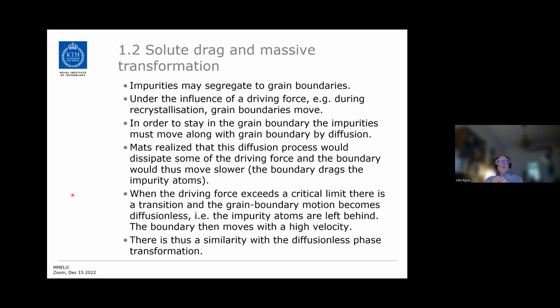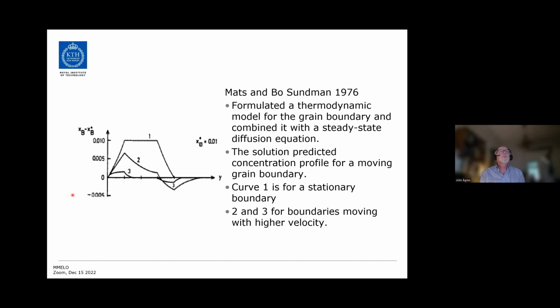And moreover, when the driving force exceeds the critical limit, there is a transition and the grain boundary motion becomes diffusionless, which means that the impurities, they are simply left behind. And then the grain boundary can move with a high velocity. So in a sense, there is a similarity with the diffusionless phase transformation. And that was, of course, realized by Mats. So Mats and Bo Sundman in 1976, they formulated a thermodynamic model for a grain boundary and combined it with a steady state diffusion equation. And then they could calculate the concentration profile in a grain boundary for different rates of migration of the grain boundary. Here is one example.